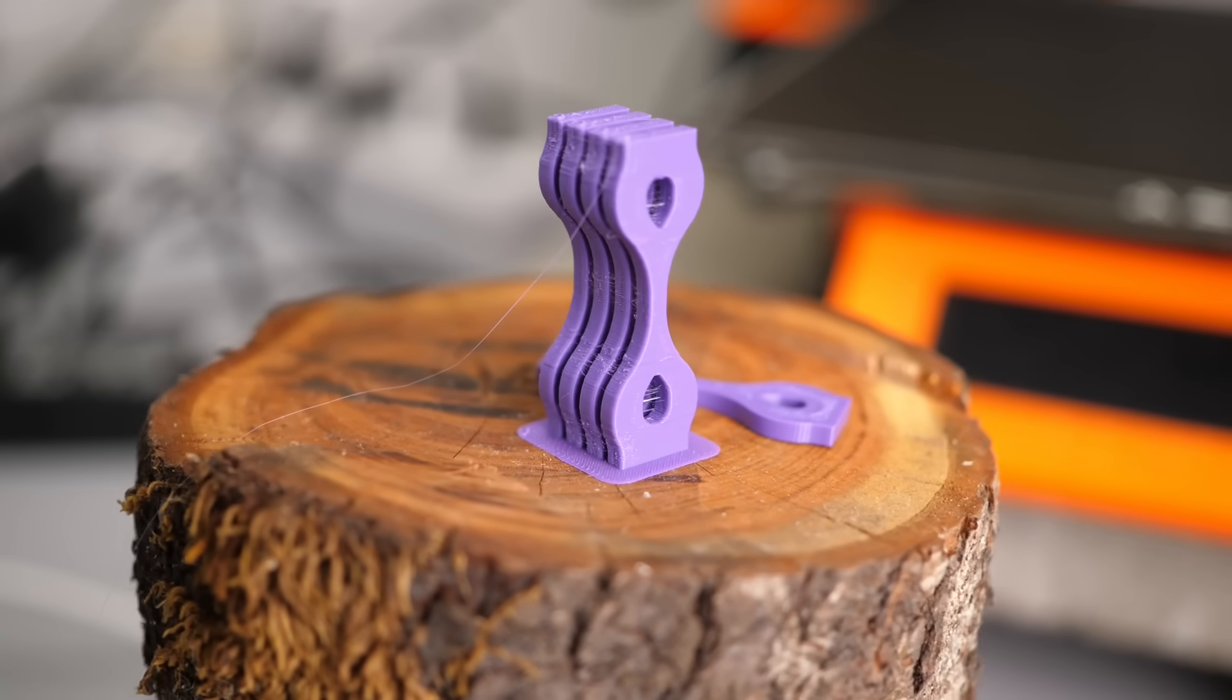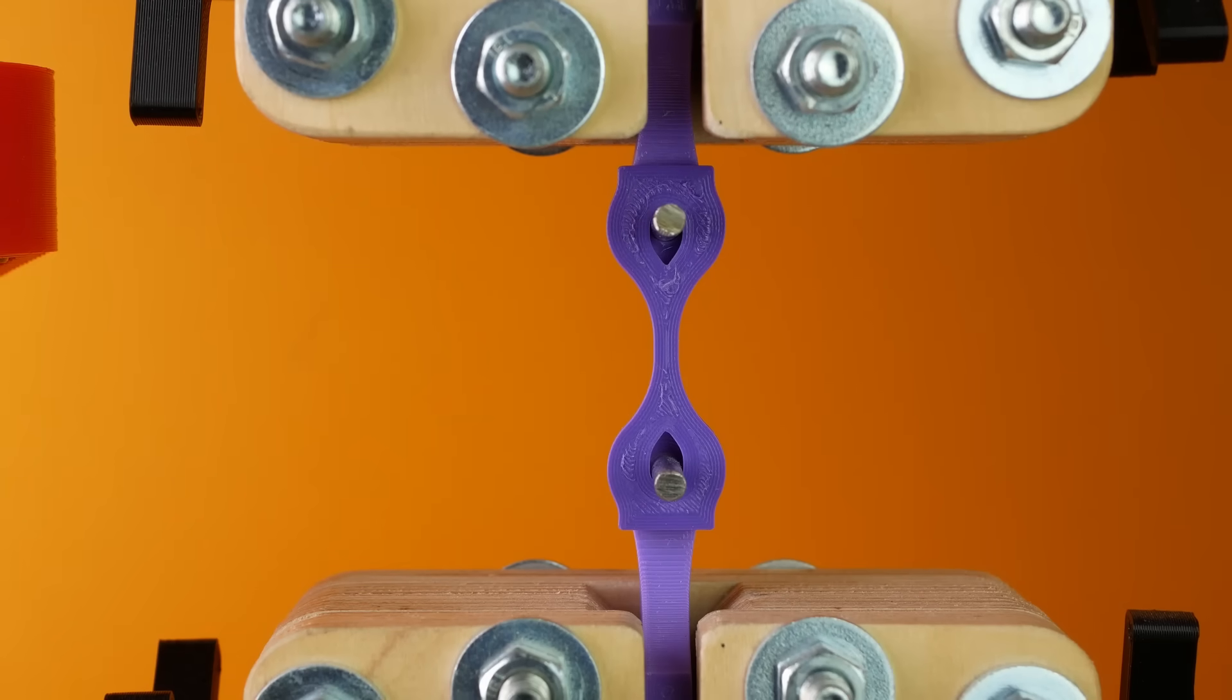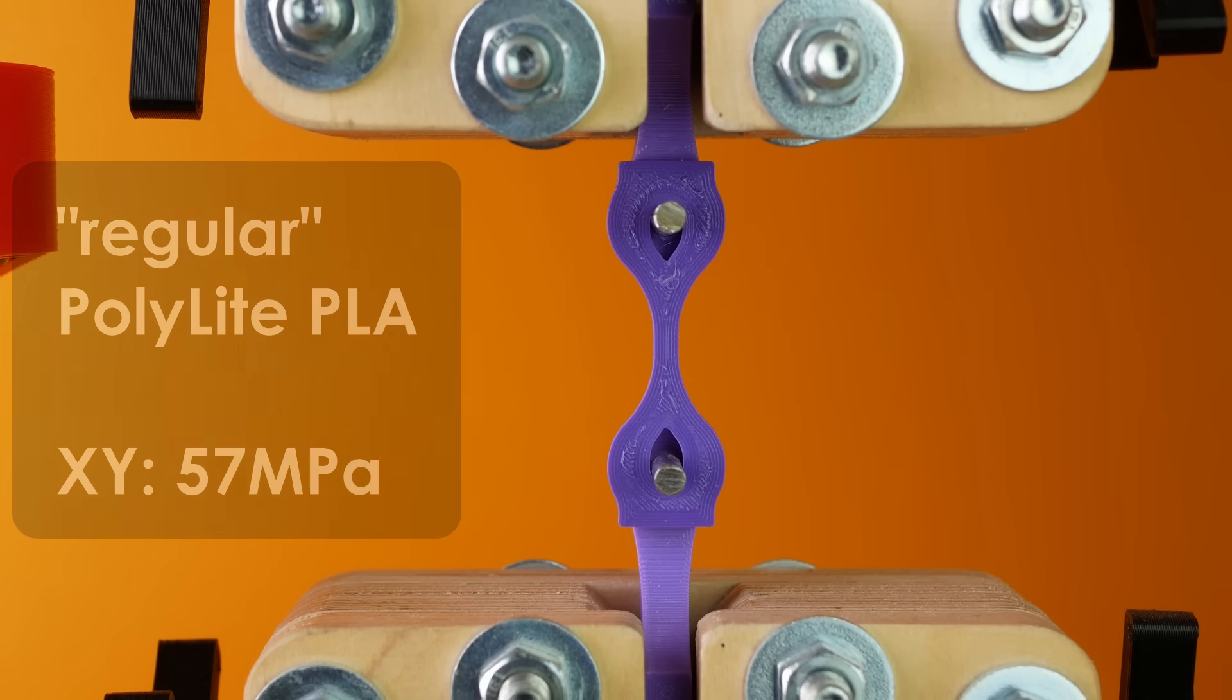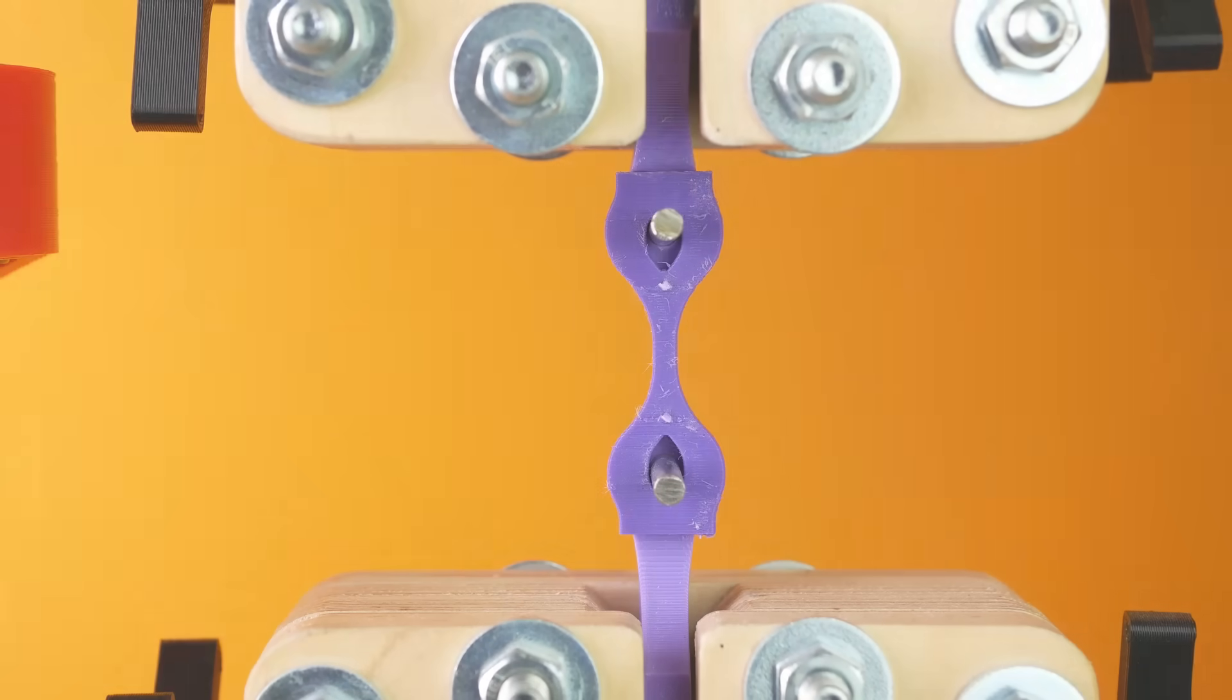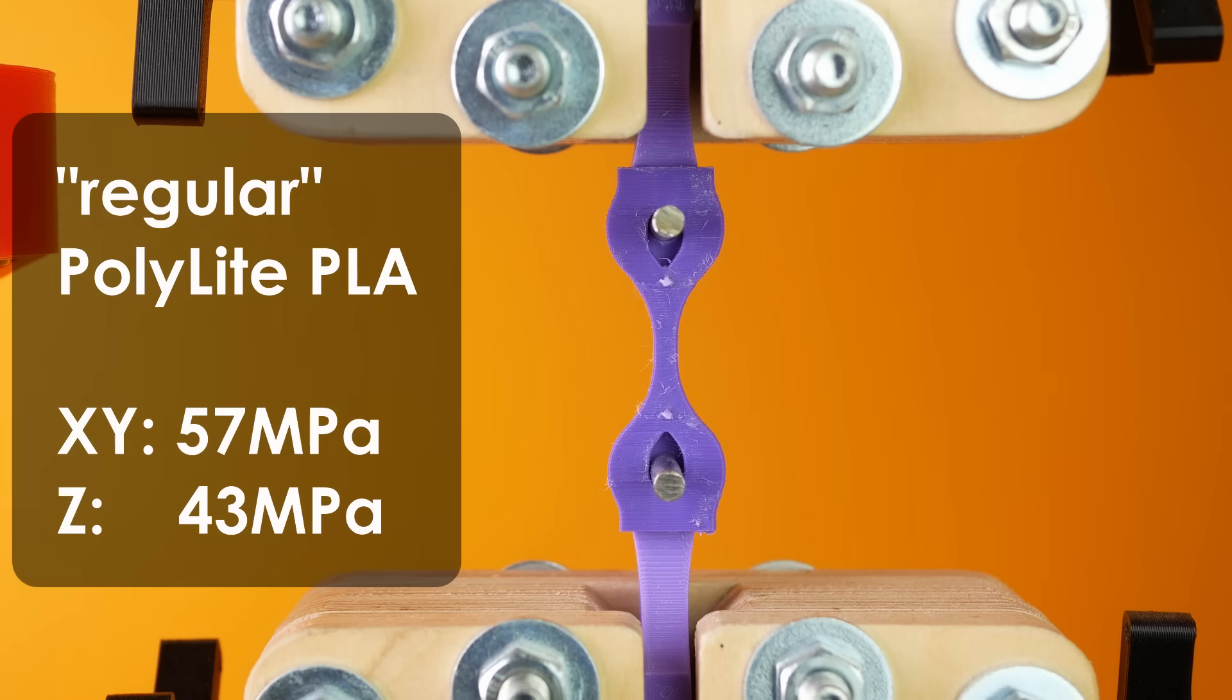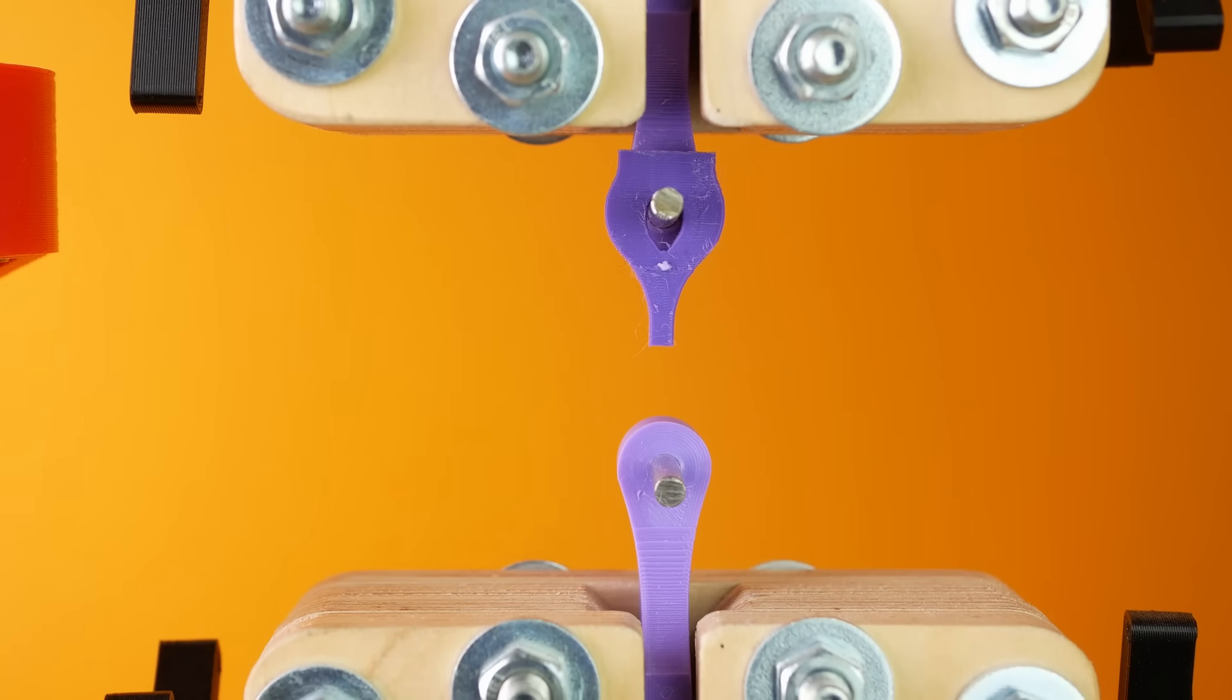PolyLite samples that were printed lying were able to bear 57MPa of stress but did fail quite abruptly and violently. The layer adhesion samples also performed remarkably good with a maximum strength of 43MPa which is still 75% of the regular strength.